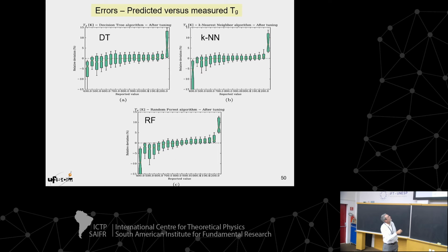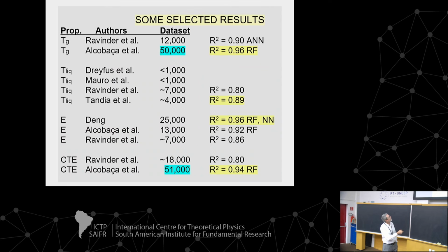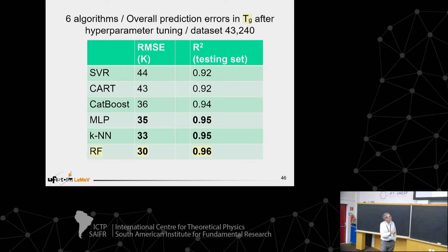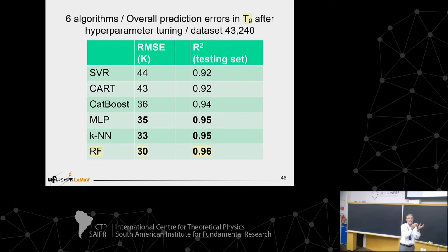This is for TG. These are different algorithms. Let me go back a little bit. See, we found that the random forest is best. Look at the R2 of the testing set. The R2 is largest for the random forest, very good for the KNN, and not so good for other algorithms. So these two algorithms are especially good for this type of problem. For other types of problems, maybe other algorithms work best.